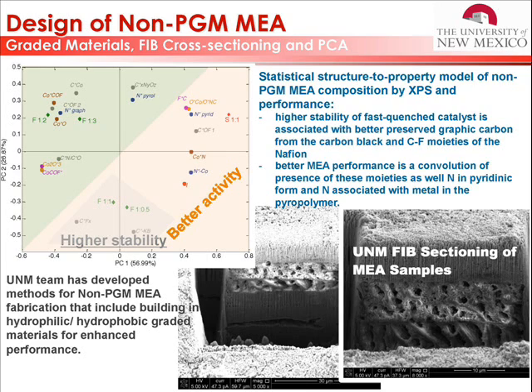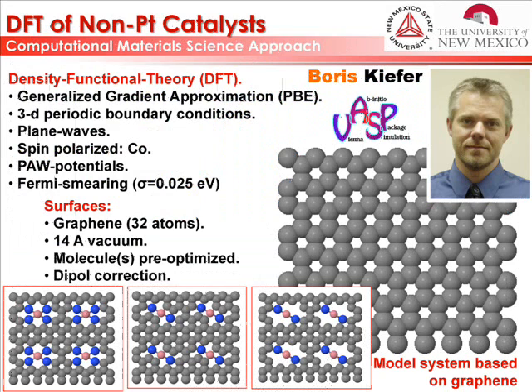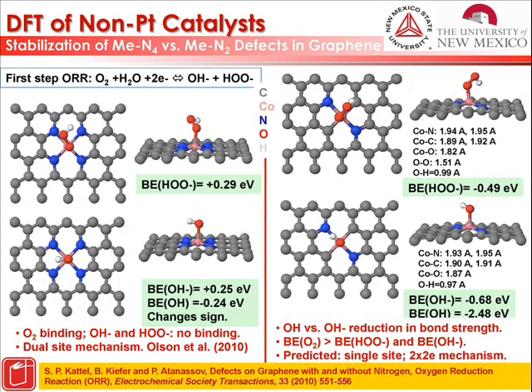This is not enough. You also need to work with theoreticians. There are also smart people, like my other associate, Boris Kiefer. He does DFT in periodic solutions, and he is solving different graphene defects. And he tells you which types of defects in graphene, N4 or N2, will stabilize hydrogen peroxide, and which will be eliminating the hydrogen peroxide to do a better mechanism.